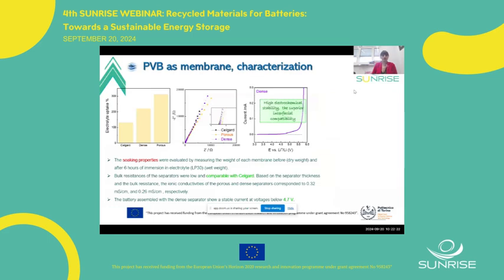So we tried to do some characterization. Some of them are shown, like uptake test, ionic conductivity, and electrochemical stability window, which are very important for characterization of the separator. We tried to compare the performance with Celgard, which is a commercial separator.